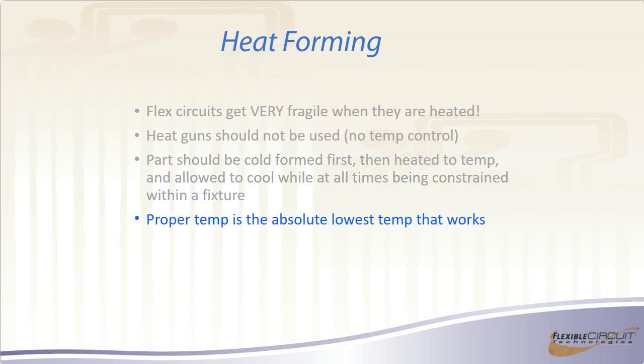And when people ask what temperature you form at, the best temperature is the lowest one that works. And I would literally start at about 150 degrees Fahrenheit and then go up from there. If you get up to 275 and it's not holding the form you want, there's no reason to go any higher, because at that point you've softened it about as much as you're ever going to. So that's kind of your range, between 150 and 275 F, but the lowest one you can use that works is your best bet.